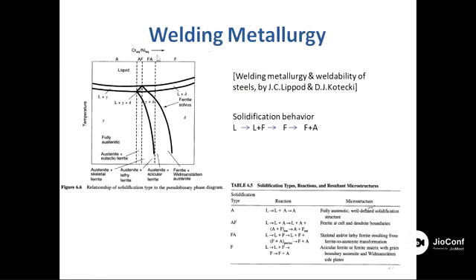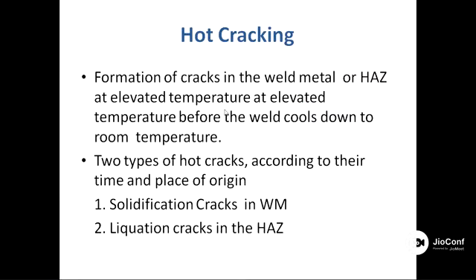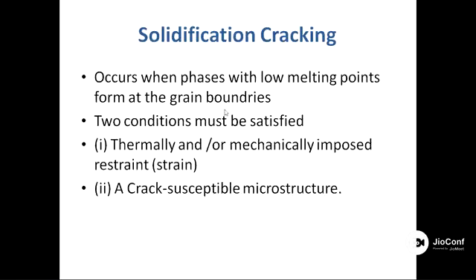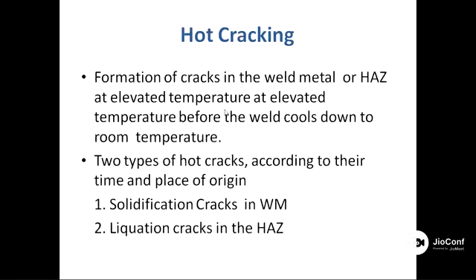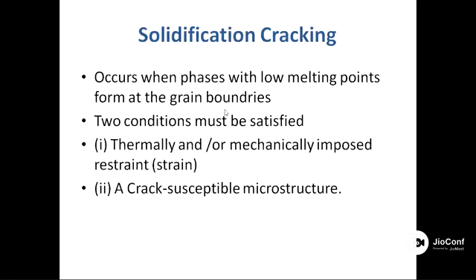So in a nutshell, what is important from the austenitic steel welding point of view is that it should solidify under AF mode, primary austenite, secondary ferrite. Then it is less susceptible to hot cracking. This hot cracking, or solidification cracking, as I mentioned, takes place in the weld metal, and liquation cracking takes place in the heat affected zone.